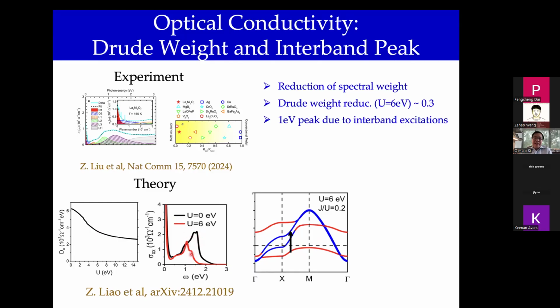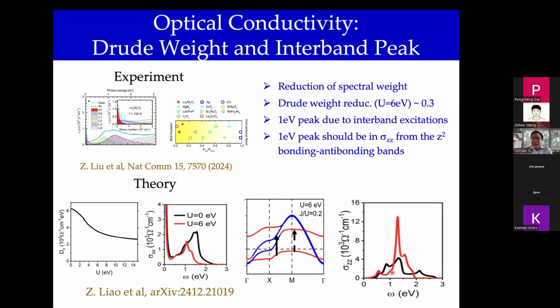So in that sense, this finite frequency part of the optical spectrum is also very informative, reflecting what these dz square and these different 3d states are doing in the real material and in the calculations in the presence of interactions. And we can propose one more test, which is that in addition to the conductivity that's measured with the polarization in the plane, it would also be instructive to do measurement for the polarization along the z-axis. And this is a calculated spectrum in the interacting case, and it will be instructive to see experimental measurement. To my knowledge, that has not been measured yet. So this is all that I want to say about the normal state.